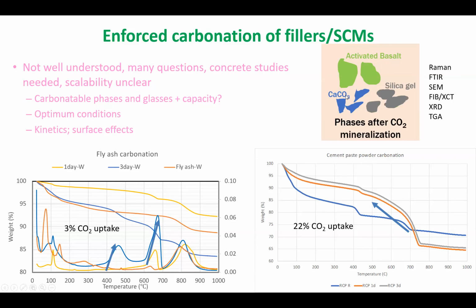So we've done a little bit of work. I mean, most of the materials, as I said, have 5 to 10%. We are trying to understand a little bit more now about the phases. The problem is, if you think about it, quantitative XRD is a fantastic technique, and it'll tell you exactly what's happening. But you already, in many of these systems, have 7 different phases. After carbonation, you form 2 more phases, right? Most of these techniques don't work when you have 9 phases which are heterogeneously distributed. So that's one of the reasons why we are interested in looking at pure phase glasses.